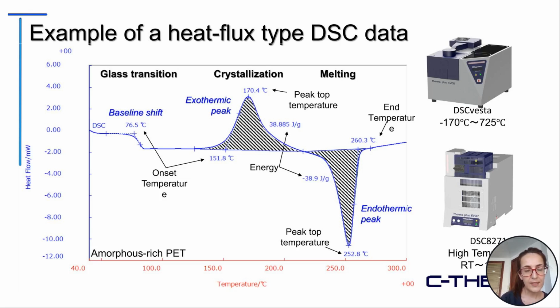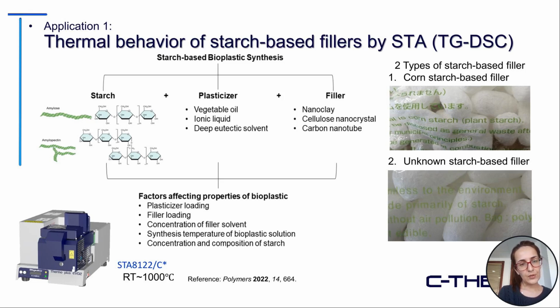Here you can see an example of heat flux type DSC data for amorphous-rich PET. Usually in amorphous materials, we can see changes in the baseline, as in amorphous-rich polymers. The first transition is denoted to the glass transition temperature. Then we have the exothermic peak, which is related to crystallization, followed by the endothermic peak, which is related to the melting temperature of the PET. In addition, we can determine the onset and endset temperatures and also the enthalpy, or energy, of the exothermic and endothermic peaks. In this example, you can see that the enthalpy of the exothermic and endothermic peaks is the same since it is amorphous.